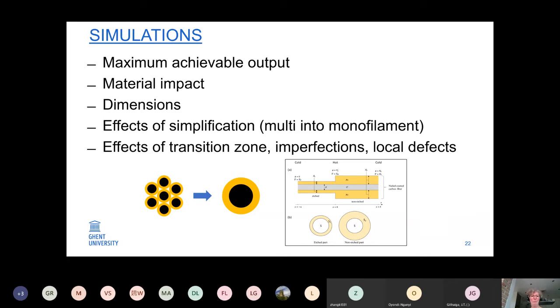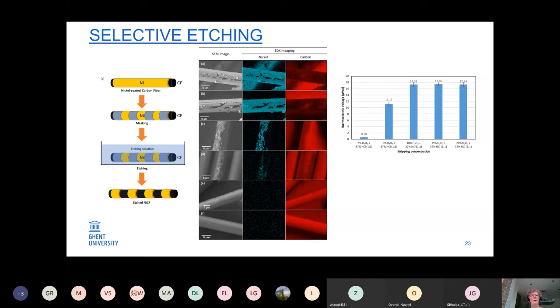Selective etching, here you can see some results. We had to elaborate a method for the etching because there was no literature. And here you can see how by increasing the concentration of peroxide, the nickel is disappearing and the carbon core becomes visible. And in the right figure, you can see the resulting thermoelectric voltage as a function of the peroxide concentration.